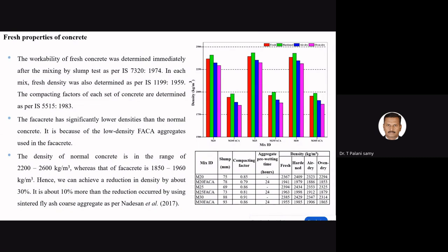These are the properties for slump, compacting factor, average pre-wetting time, and the density also: hardened density, air dry and oven dry density. You can see here how the density changes. Even if you look at the conventional concrete, the weight is more, right? Suppose it's around 2300 kg per m3. But in the case of M20 FACA, it is around 1900, or say around 2000, right? So if I could get below 1800, I could claim it as a lightweight concrete, but that is not happening nowadays. So these are the densities of the hardened state, air dry and oven dry densities also.